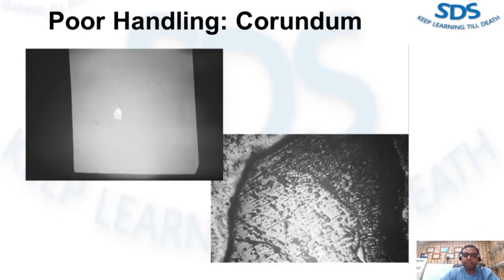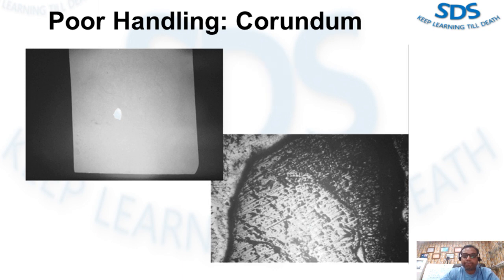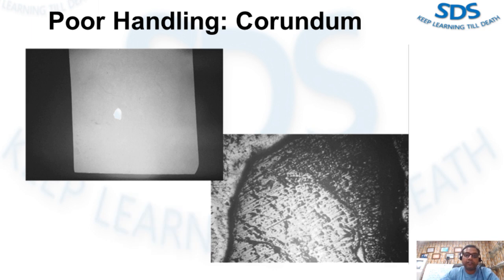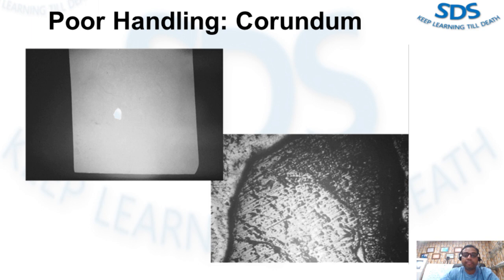Corundum: this figure shows an x-ray of a hard spot found in a casting, and a photomicrograph reveals that the hard spot is Al₂O₃ corundum — the hardest material next to diamond. This form of aluminum oxide is found at the metal line on the walls of the furnace. It develops extremely fast in electric furnaces if there are air leaks or an excessive amount of oxygen is present. The corundum got into the casting when personnel were not careful while cleaning the furnace. To prevent formation of this material, the furnace must be tightly sealed.